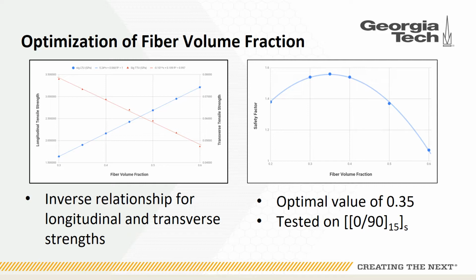When analyzing the stresses and strains of our initial laminate, it became apparent that each lamina was much closer to failing in the transverse direction than the longitudinal. In addition, the longitudinal loading on the laminas was less than half of their failure strength. To fix this issue, the team investigated the effect of changing the volume fraction of our laminas. The graph on the left shows the effect of changing the fiber volume fraction from 0.3 to 0.6 on the tensile strengths of each lamina. As shown, the longitudinal tensile strength increases as the fiber volume fraction increases, while the transverse tensile strength decreases. Therefore, it was beneficial to decrease the volume fraction.